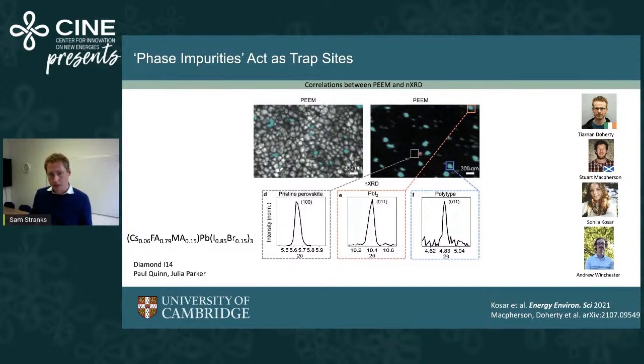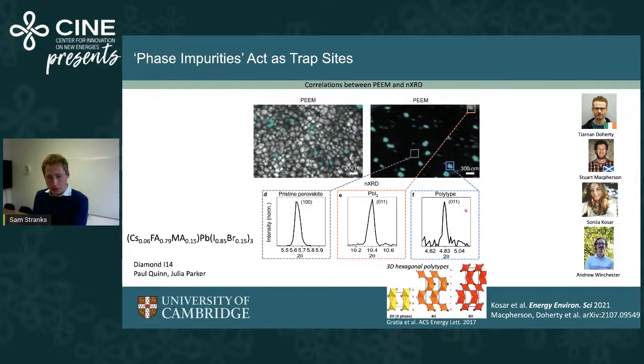And so we can look, for example, at a region that's more pristine and away from these trap states, we see a pristine perovskite, which is what we would expect. But then when we look at these trap clusters, what we see is that they correspond, in fact, to other phases, so other phases either of perovskite or other non-perovskite phases. And so this is an example of a lead iodide region here. And we also see these polytype regions, these hexagonal polytypes.